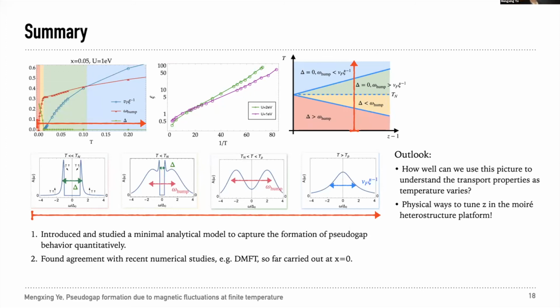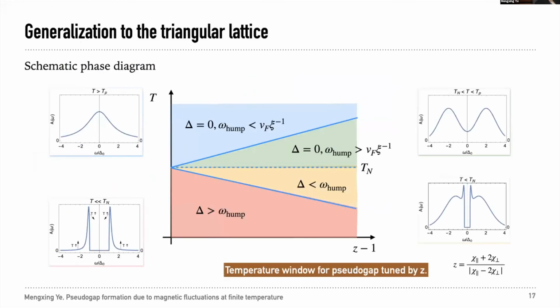I have one additional question as well. Was spin rotational invariance very important in your calculation? And do you think if you add spin orbit coupling, the results will change to some degree? Very schematically, varying the spin orbit coupling essentially will gap out some of the ghost modes. If they are still weak and we can still keep them, they just become a little bit massive, which is similar to tuning this z factor. So there is a way to do that for the triangular lattice, I think that is one way to actually tune this z effectively. And for the square lattice, we need to think more about what the diagrammatic series is, so that kind of changes some conditions in the diagrammatic summation.